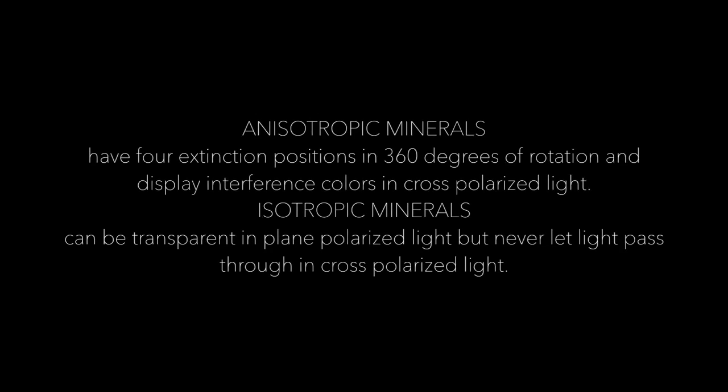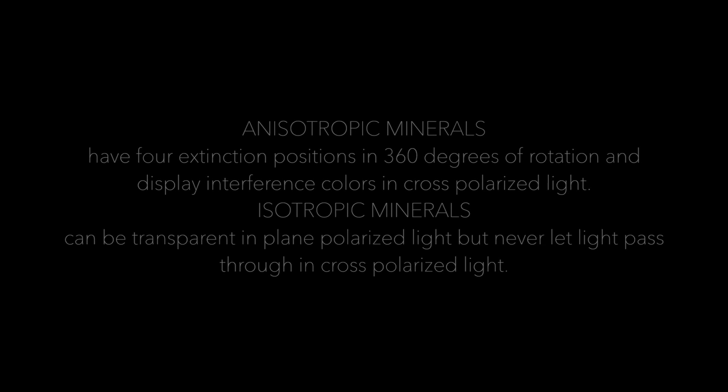In summary, anisotropic minerals have 4 extinction positions in 360 degrees of rotation and display interference colors in cross-polarized light. Isotropic minerals can be transparent in plane polarized light, but never let light pass through in cross-polarized light.